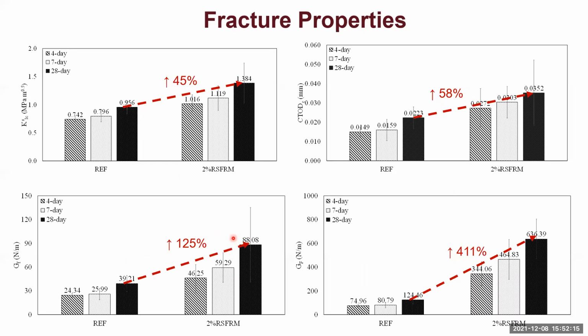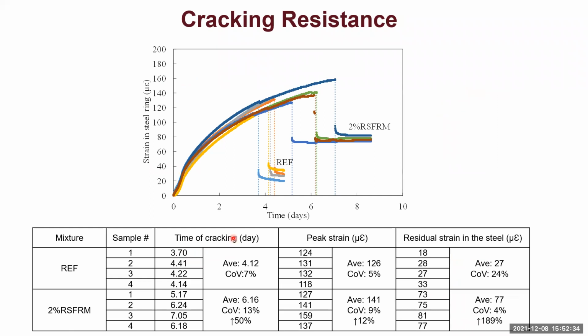We also had some fracture property test results here. As you can see, by adding fibers, the stress intensity factor, the crack tip opening displacement, and the fracture energies all improved significantly. We also have the cracking resistance results showing here. Again, adding fibers improves the peak strain, and we also have a higher level of residual strain after cracking, and the cracking time also improved by about 50% compared to the control sample.